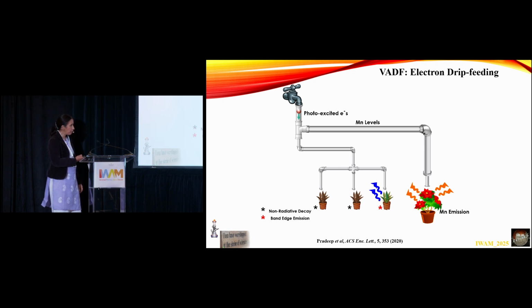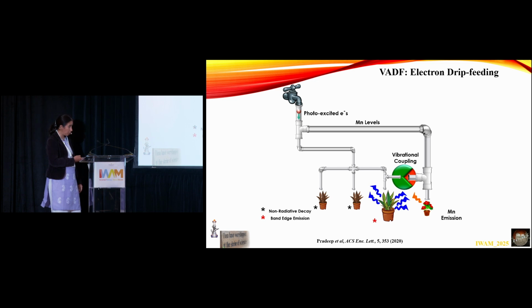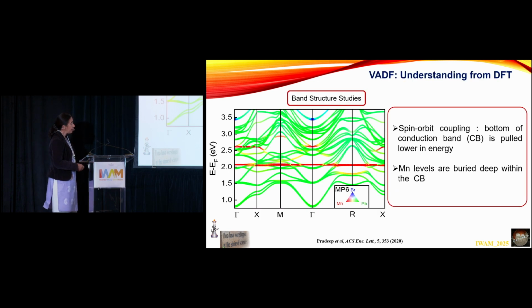And normally it would just emit in its own time. But with vibrational coupling, it does not emit through the manganese lifetime, but couples back specifically to the radiative channels of the host and deprives it of the non-radiative channels. This is very interesting because what I'm talking about is like a storage of electrons inside the manganese, and as and when it recombines radiatively, it provides a few more electrons.